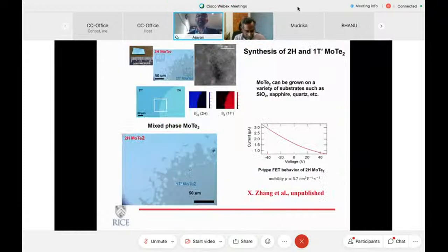Just to go back a little bit, if I try to grow molybdenum telluride under normal conditions without really controlling what phase is formed, you get a distribution of both the phases. So if you look at the image on the left, you can see that there is a 2H MoTe2 and 1T prime MoTe2 formed on the same film, if you actually just grow them.